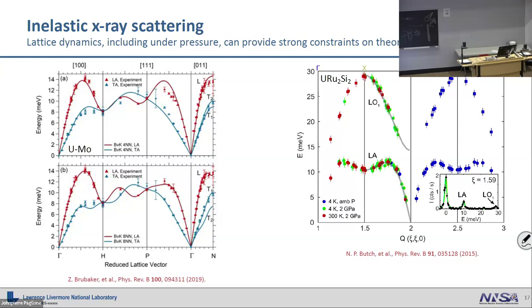It can be really useful if you're finding weird phase transitions and you want to understand why there's a phase transition. You may come to the inelastic spectra and look for soft modes or something in the phonons to see if that's what's driving it. Is it an elastic thing or is it a magnetic thing? If you don't know, this is a great way of starting to ferret that out.